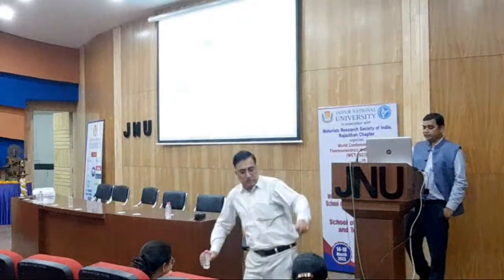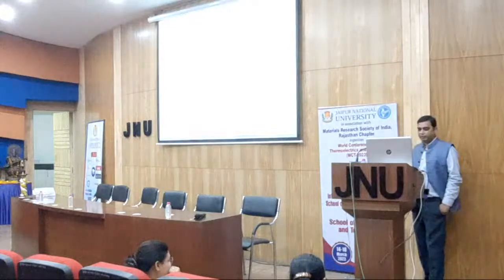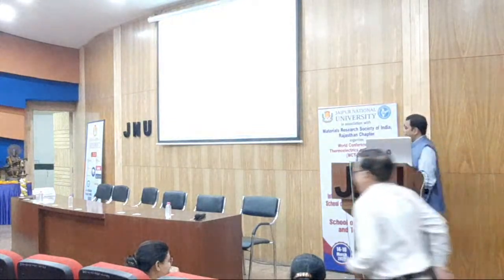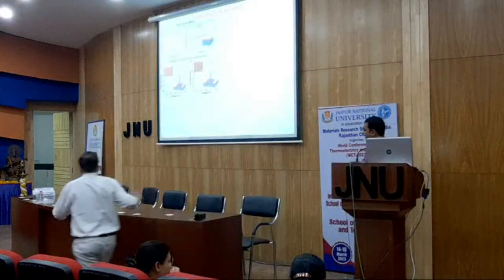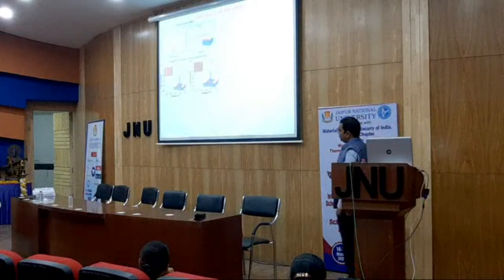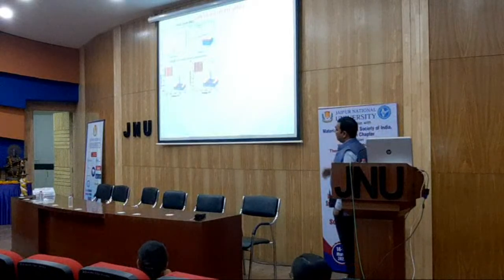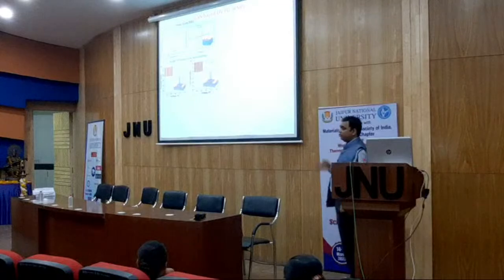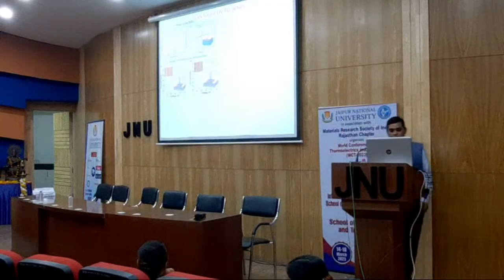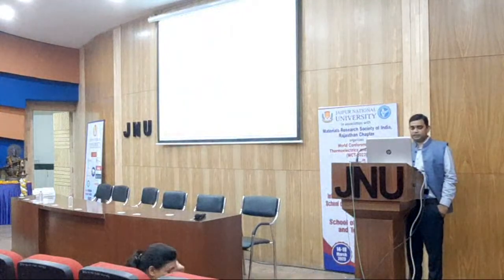Then we have analyzed the impact of substrate orientation, where by choosing different substrates like C-plane to A-plane, how the device is performing. You can see the IV characteristic tells that C-plane sapphire is showing ohmic behavior, while A-plane sapphire substrate is going towards the Schottky behavior. So then multi-layer structure is showing different pathways.